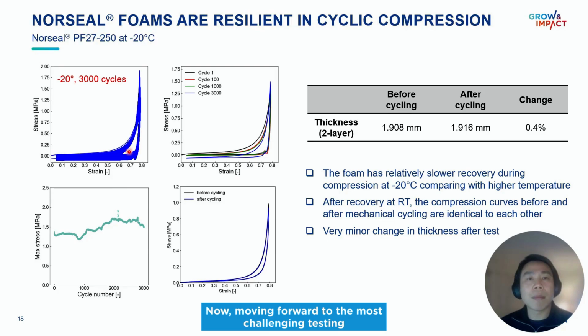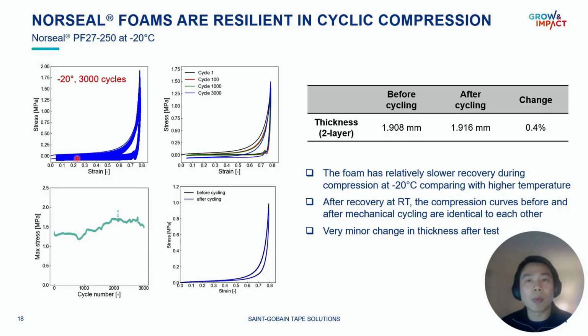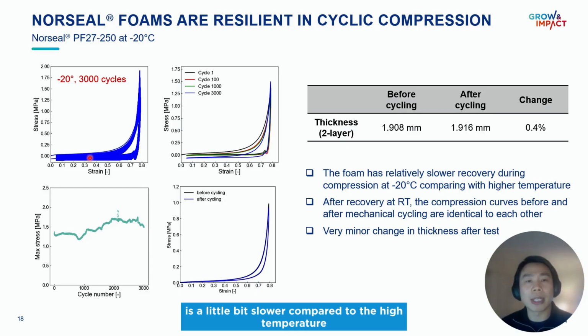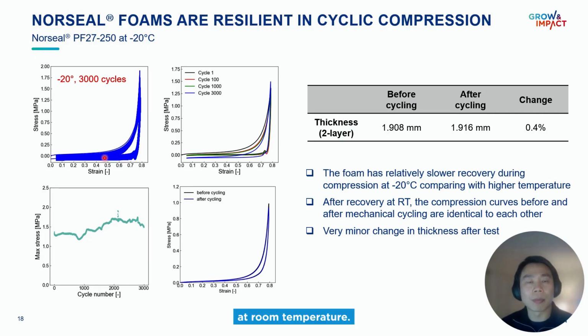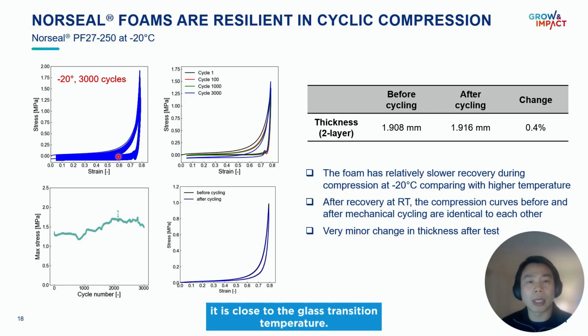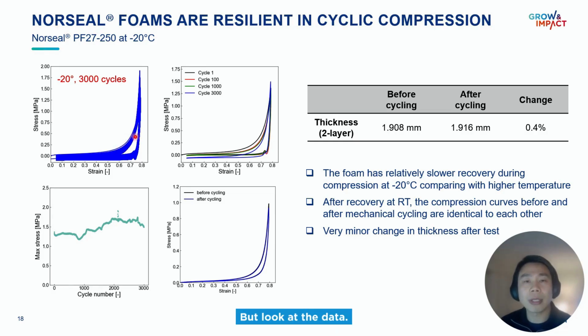Now, moving forward to the most challenging testing at the sub-zero temperature, minus 20 degrees C. At this cold temperature, we see the foam recovery is a little bit slower compared to the high temperature at room temperature. This is pretty normal for a polymer because at this cold temperature, it is close to the glass transition temperature. Viscoelasticity becomes more significant in this case. But look at the data.